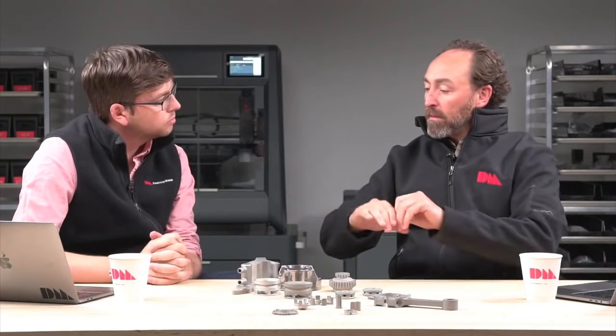And that's the key. If you don't have reliable, repeatable shrinkage, you don't have a reliable process. And the way they did this was by using certain sizes and particle size distributions of powder. And so we've done the same thing in our printers. We've designed the printing process around powders that have reliable and repeatable sinterability. So they pack very uniformly when they're in the powder form, and they drive out porosity very uniformly during the sintering process. And because of that, you get the same type of repeatable and reliable shrinkage process as you do from metal injection molding. So you can think of us as leveraging decades of technology development in the MIM industry.